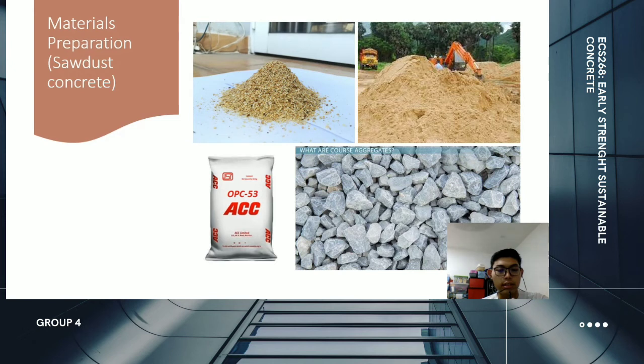Alright, so this is the materials preparation for sawdust concrete. The same materials: river sand and coarse aggregate with a 20 mm maximum size, and OPC 53, the specific grade. For sawdust, we obtain it and dry it under the sun for 24 hours, and then we put the sawdust in a paper bag to stop it from absorbing water from the air.